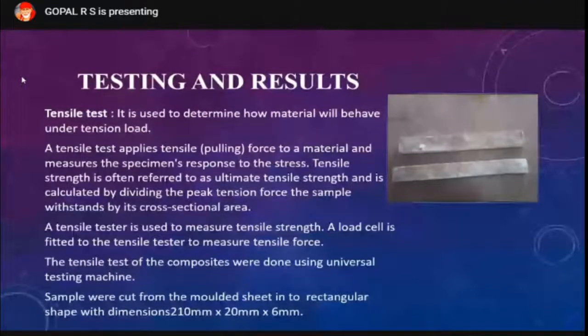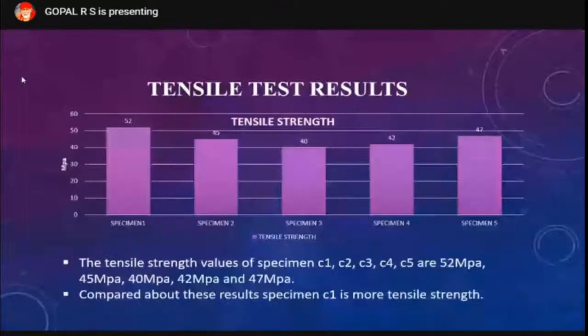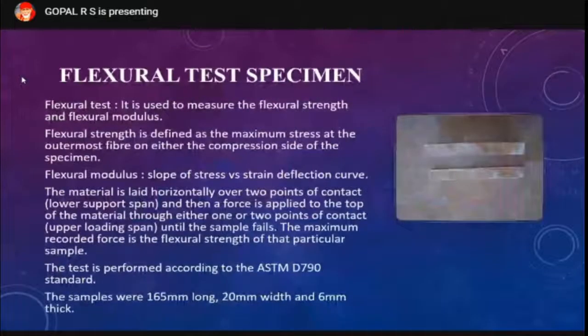The tensile test of the composite was done using a universal testing machine. The samples were cut from the molded sheet into a rectangular shape with dimensions 210 mm long, 20 mm width, and 6 mm thick. Tensile test values of the specimens are shown in the bar chart. When comparing the results, specimen C1 has more strength. Next one is flexural test.